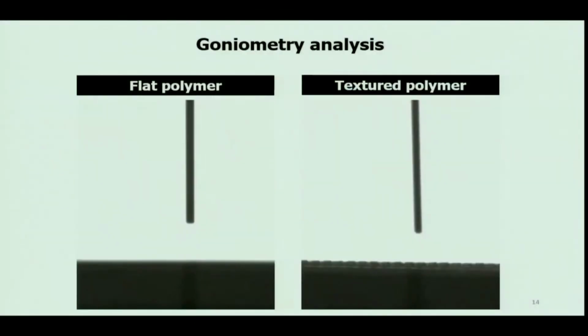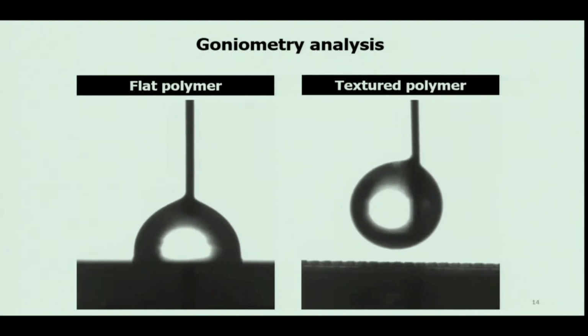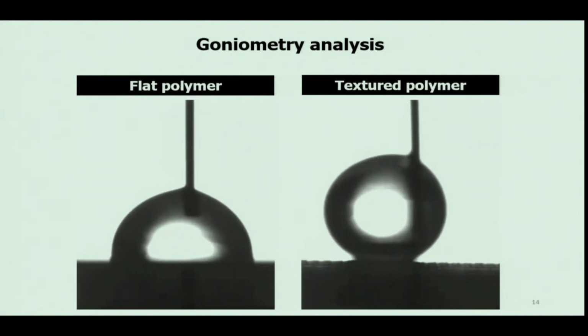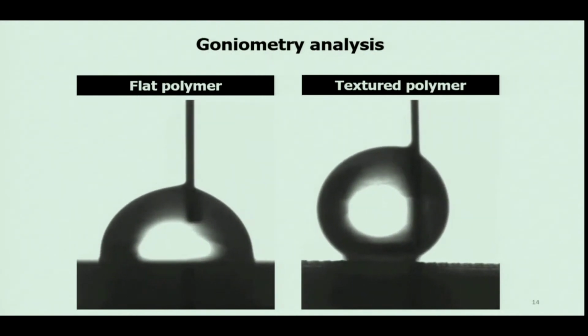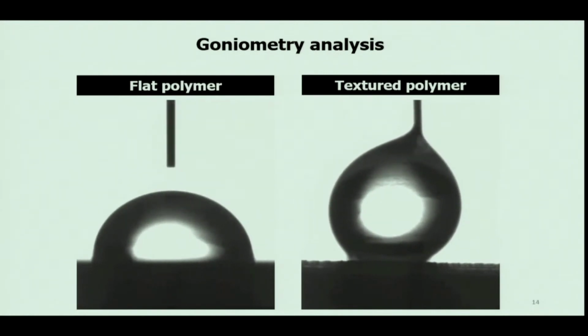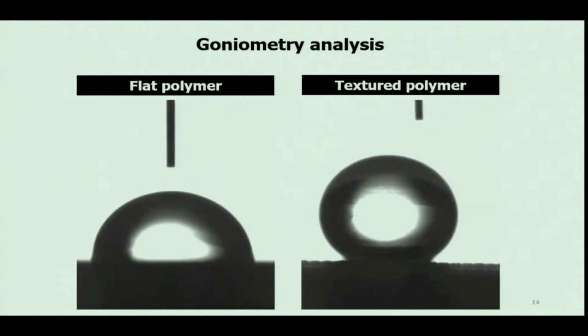Now I'm going to show you two quick videos from my recent results from the goniometry analysis, comparing a flat and a textured polymer. And in the goniometry analysis, a syringe puts a droplet of water on top of the surface and analyzes the contact area between the droplet and the material. And now you can clearly see how a textured polymer enhances the hydrophobicity of a surface.